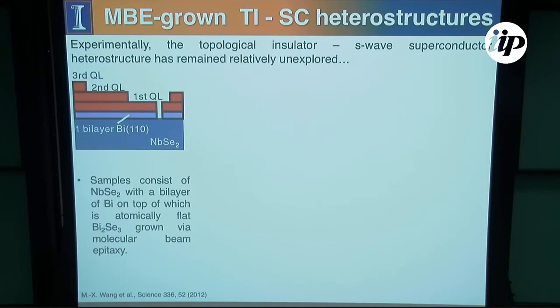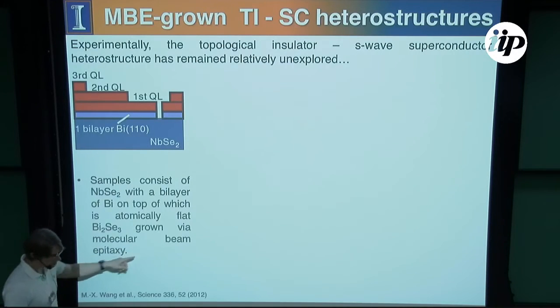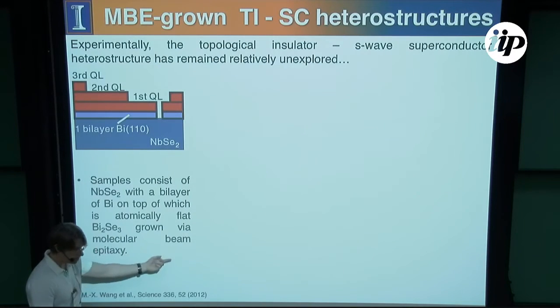And so on top of this, they grow a bismuth layer because what they're interested in doing is making sure that the strain is not too terribly difficult. And then they start growing quintuple layers of topological insulator via molecular beam epitaxy. Based on proposals that I've reviewed over the years, you can use MBE for a bunch of different things. Depending on their productivity, it could be make-believe experiments, or also, depending on their budgets, it's mega-bucks evaporators.